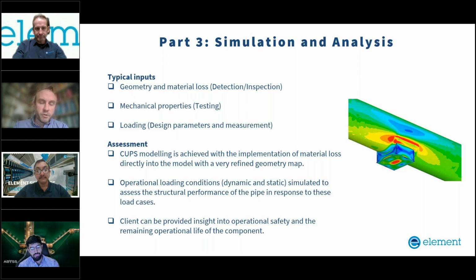So what we were able to do by applying the typical design loads that we would expect for this plant, but also taking into account the stresses that Basab was able to identify as local stresses during the operation, we can validate what's actually going on in the pipework using those stresses that were found, and make decisions as to how we should load the pipework in our simulations to be able to feed into an accurate fitness for service assessment.